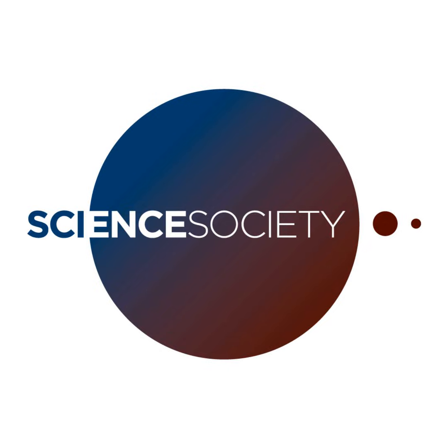The best results were gallium-aluminum. GS would be Galinstan, so that's a gallium indium tin alloy, quite expensive. That works, but not as well at different ratios. And then they also tried gallium, aluminum, indium, and so forth. So the best was gallium aluminum, and further, I've got another plot on the next slide.